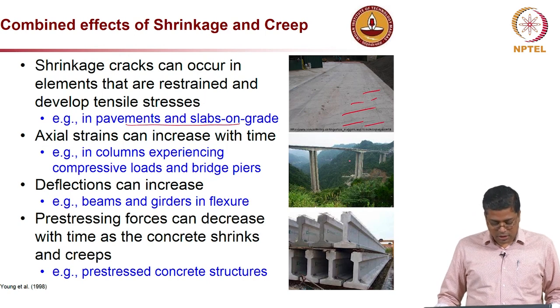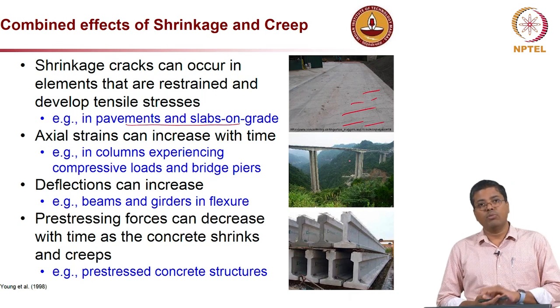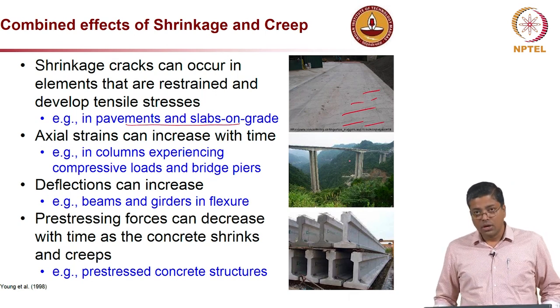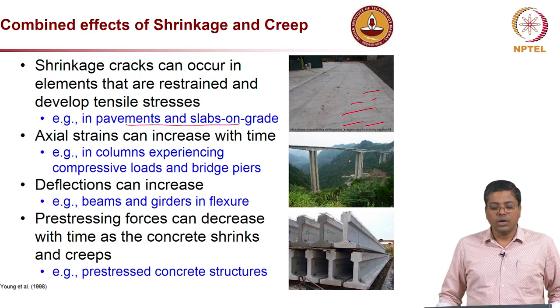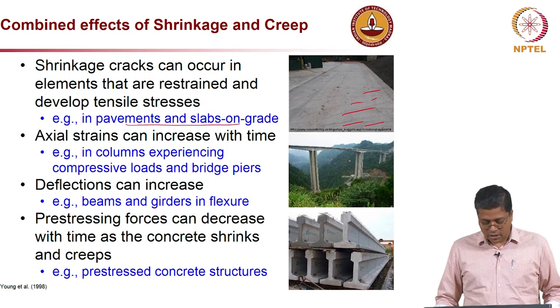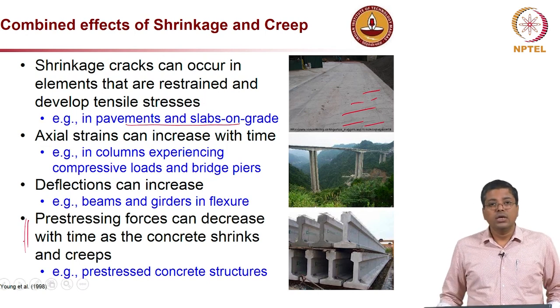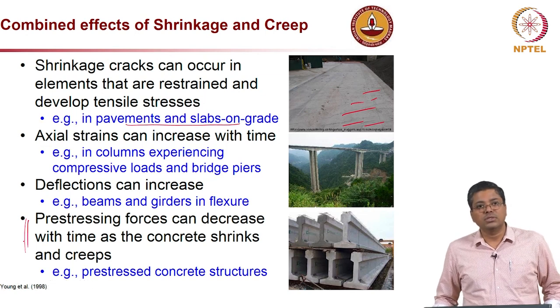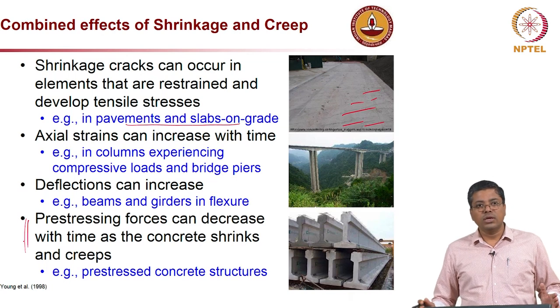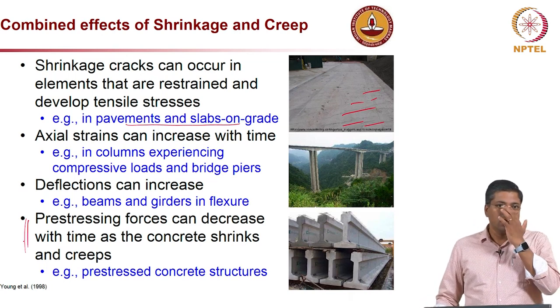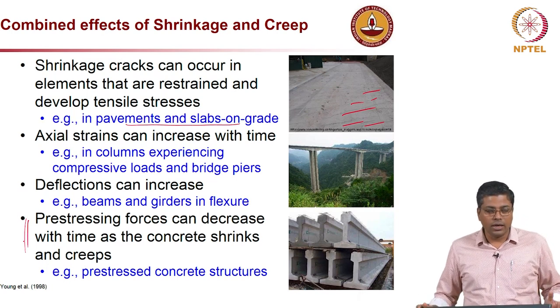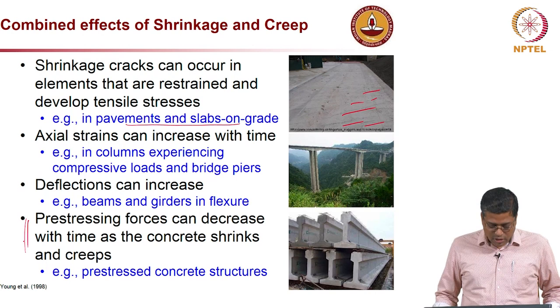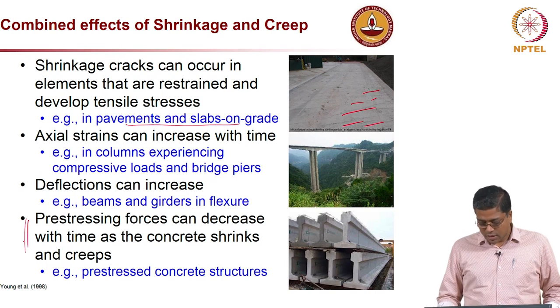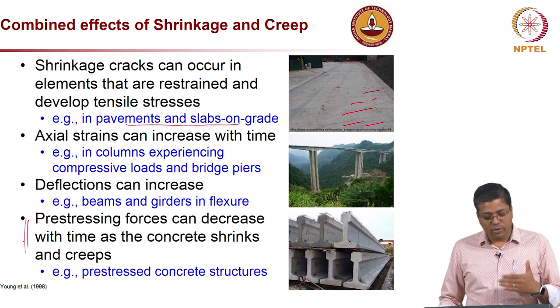You can have significant effects due to shrinkage, and those effects could be in the form of compression of the columns, or even significant deflection on the girders, especially if they are pre-stressed concrete girders and the concrete creep resistance is not very high. Then, because of the pre-stressing forces, the concrete can creep and the length of the girder could reduce, which will result in the loss of pre-stress, which eventually will lead to significant deflection. So these are very important phenomena, especially when we talk about long span and large structures.